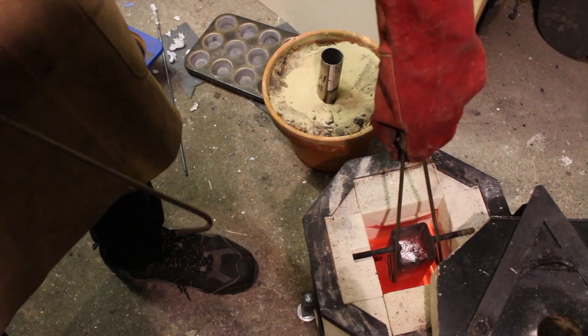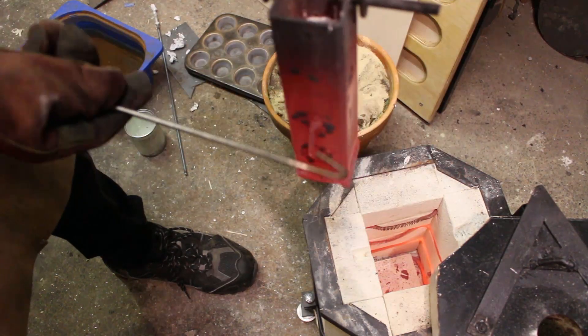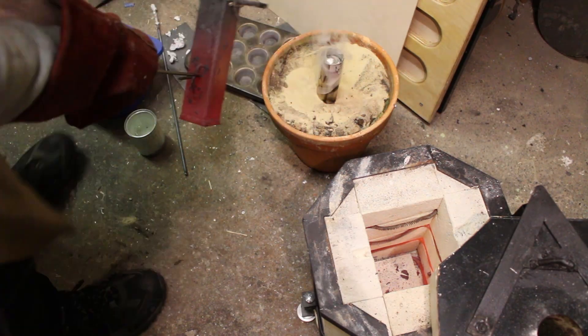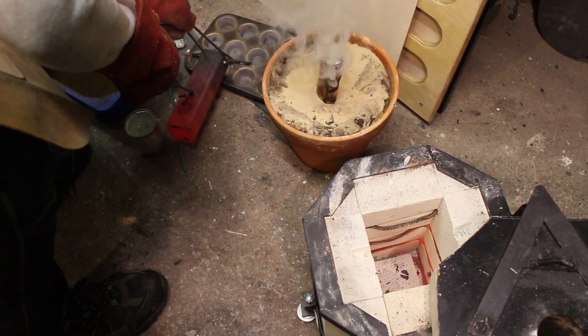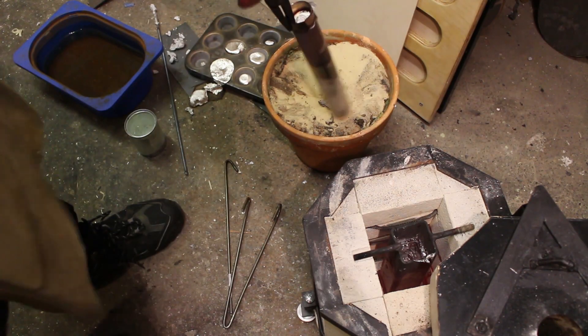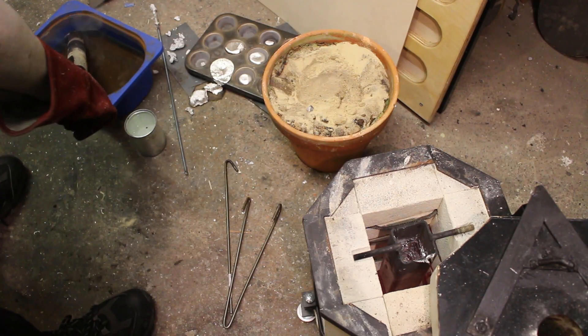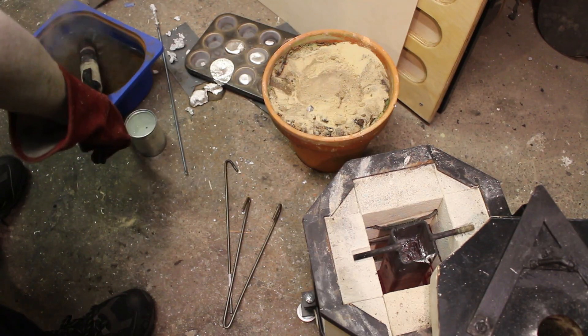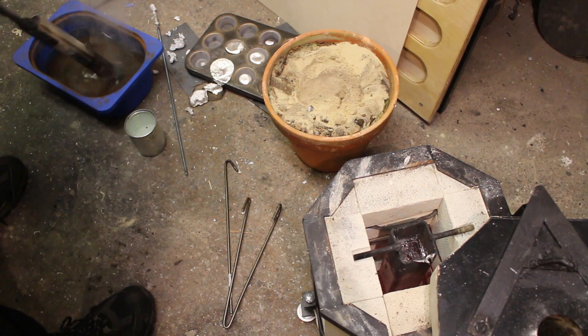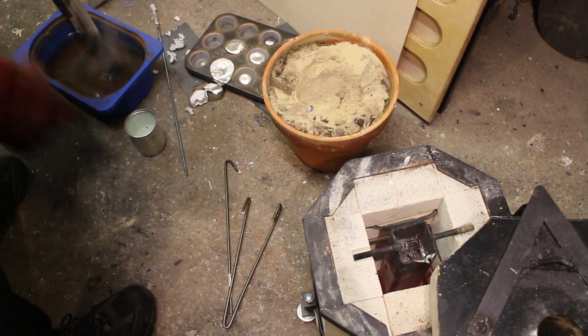When it came the time to cast I pulled the steel crucible out of the forge and basically poured it into the tube that was sticking up out of the sand and around the knife handle. I filled it up pretty much all of the way, cast the rest into ingots, and then took the knife out of the sand and cooled it down as quickly as possible in some water. This is trying to minimize the amount of heat exposure to the blade since the blade is already hardened and if it gets heated up too much by the aluminum then it will become soft again.